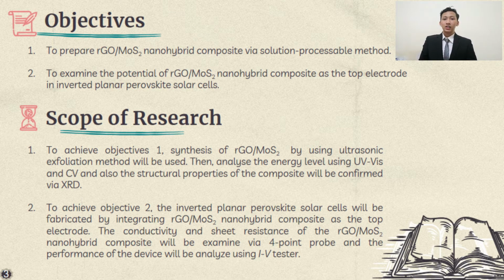Then, we will analyze the energy level and also the properties of the composite via X-ray diffraction, UV-Vis spectroscopy, and cyclic voltammetry. To achieve the second objective, the inverted planar perovskite solar cells will be fabricated by integrating RGO MoS2 nanohybrid composite as the top electrode. The conductivity and also the sheet resistance of the RGO MoS2 nanohybrid composite will be examined via 4-point probe, and the performance of the device will be examined via IV tester.